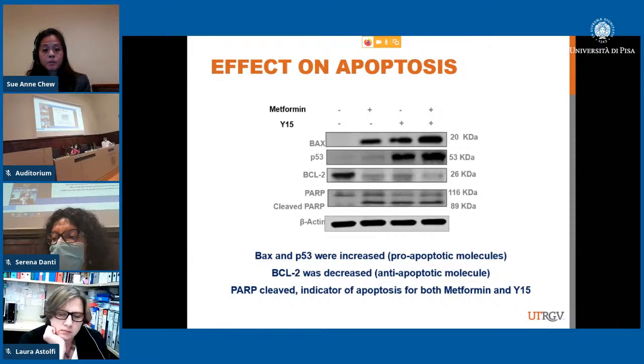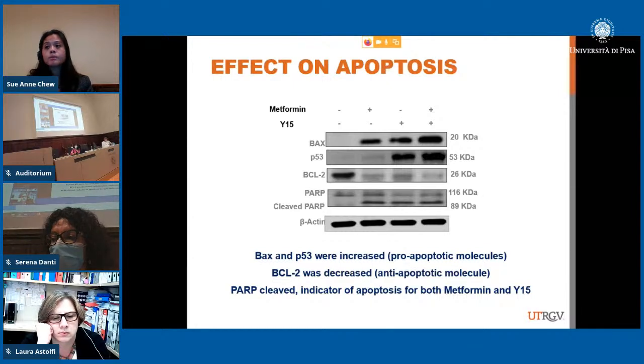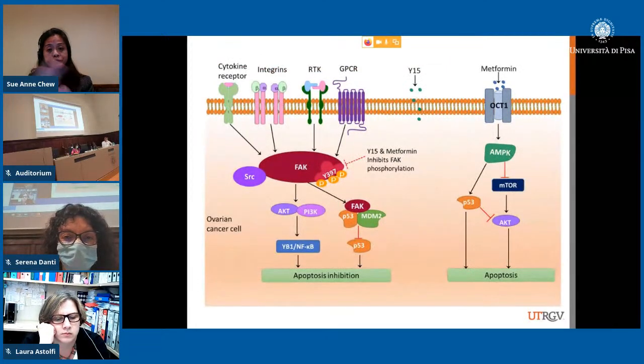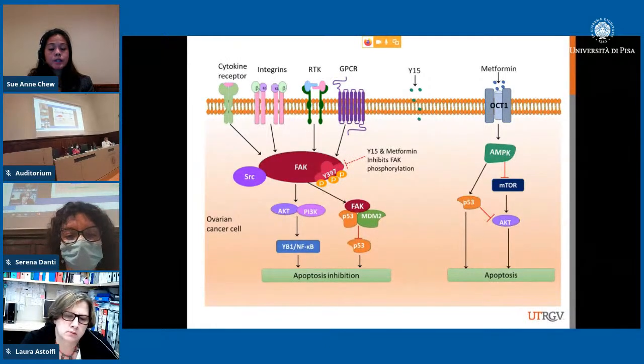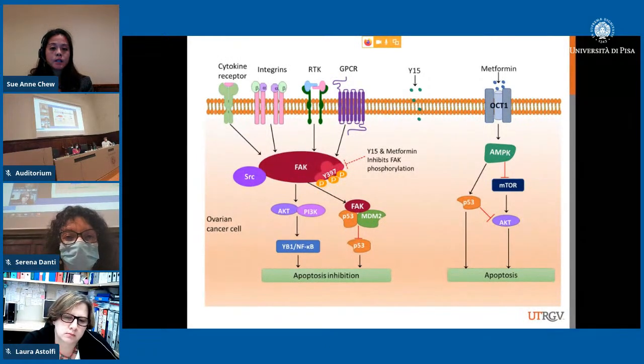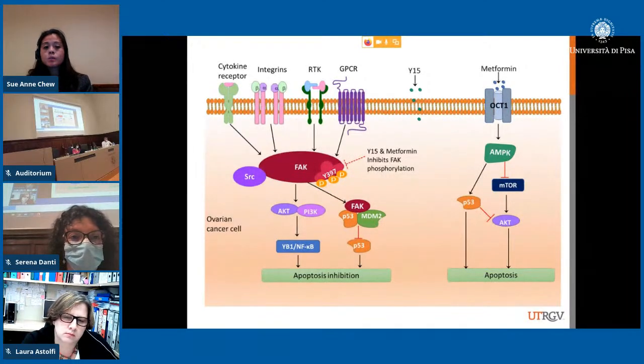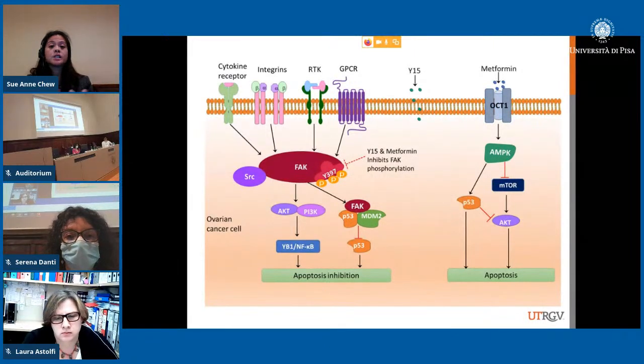So all this happens with apoptosis. We saw that BAX and P53, the pro-apoptotic molecules, were increased. BCL2, which is the anti-apoptotic molecule, was decreased, and PARP cleavage, which is an indicator of apoptosis, was also increased for both metformin and Y15. And usually with the combination we see a stronger effect in apoptosis compared to the solo. Just what my collaborator Dr. Levy's hard work has shown for this part is that Y15 and metformin are able to inhibit FAK phosphorylation and cause that synergistic effect.